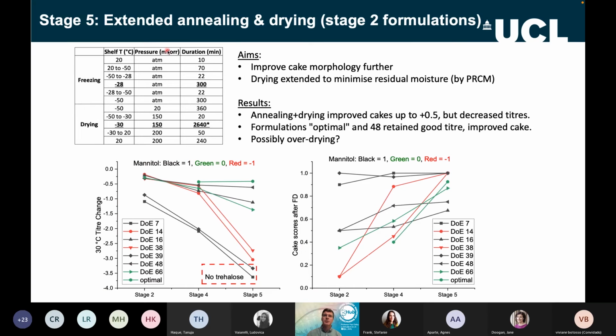Another stage we did was to say, well, if it's working, should we extend it, like do longer annealing steps and also dry the samples even more? So at the secondary drying, we left it for a lot longer so that you get rid of as much moisture as possible. So a really long duration for that. And that did improve the cake morphology. You can see what's going on overall with titer and cake score with these two plots left and right for the different stages. So stage 2 is without annealing, stage 4 is with annealing, and stage 5 is with extended annealing and drying.